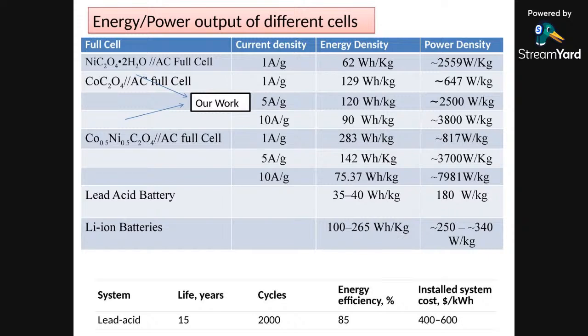So at a higher current rate, when we go for the battery kind of current like 1 ampere per gram, the cobalt nickel oxalate can generate even 817 watt per kg, and the energy density is also close to, the power density is also even close to the range of the lithium ion batteries for the cobalt nickel cell. So see, cobalt.